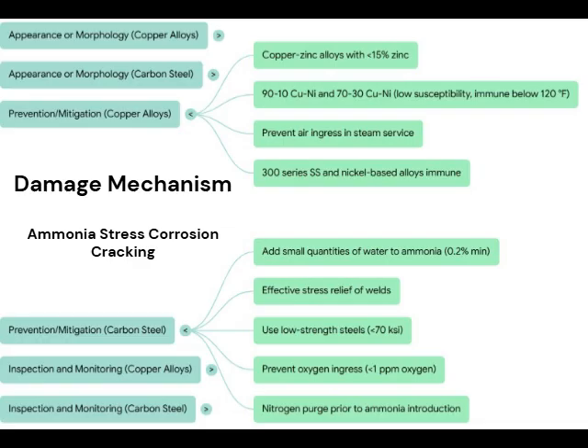Let's start with copper alloys again, since high zinc is the problem. The simplest fix is just don't use high zinc brass. Specify alloys with less than 15% zinc. Or just avoid brass altogether? Or avoid it, right? Often they'll jump to materials that are much more resistant, like copper-nickel alloys. You hear about 90-10 Cu-Ni or 70-30 Cu-Ni. Those are pretty much immune to ammonia SCC below about 120 degrees Fahrenheit, 50 C, which covers a lot of cooling water and steam systems.